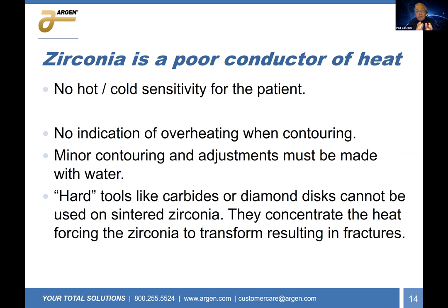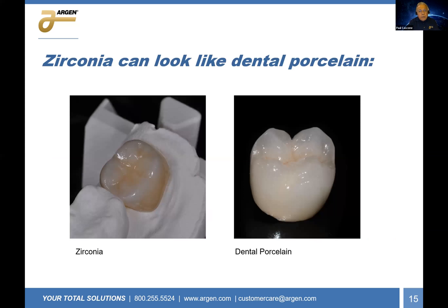Nowadays, they have tools made for zirconia that are diamond impregnated and can open the embrasures because they're diamond-impregnated rubber, and they don't concentrate the heat and they'll still cut through the zirconia. So again, the property of zirconia that's very good does cause us some issues with processing.